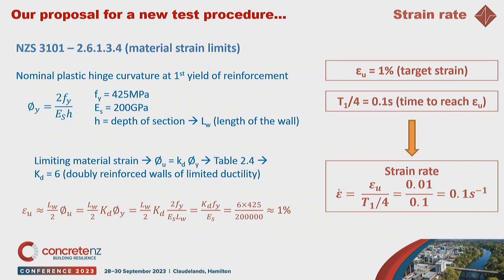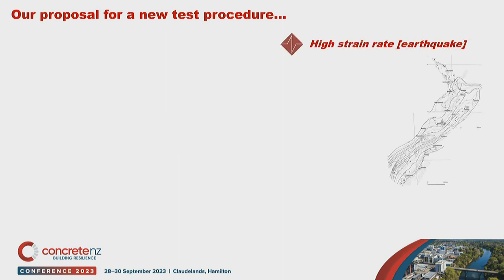If we flip the hypothesis, having a more ductile structure, epsilon u would be higher, 0.02. But also T1 over 4 would be 0.2 instead of 0.1. So it's kind of the same number. So we got it, and therefore that's a consideration.